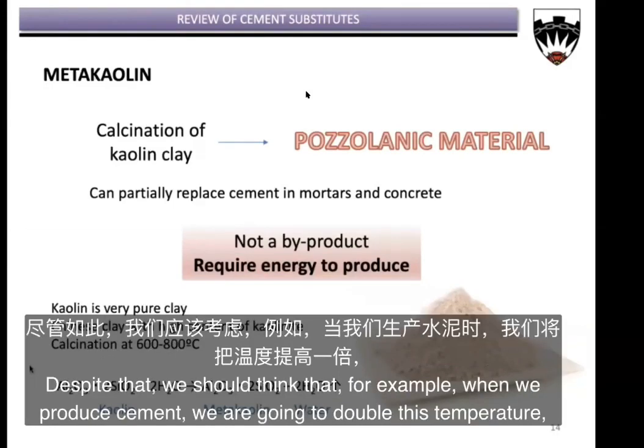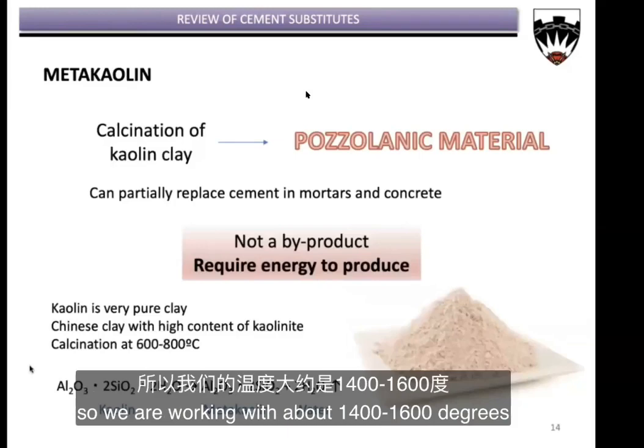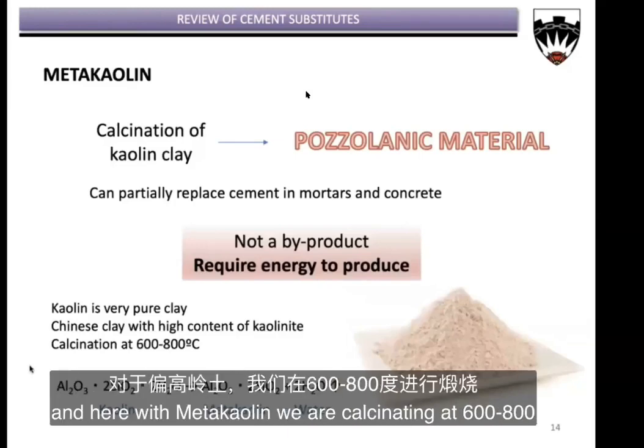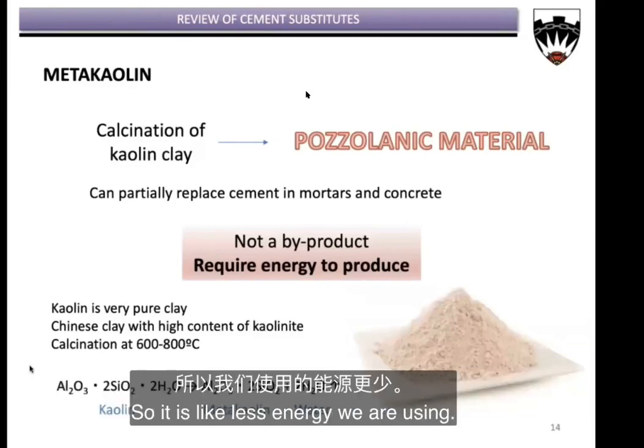Despite that, we should think that, for example, when we produce cement, we are going to double this temperature. So we are working with about 1,400, 1,600 degrees. And here with metakaolin, we are calcinating at 600, 800. So it is quite less energy what we are using.